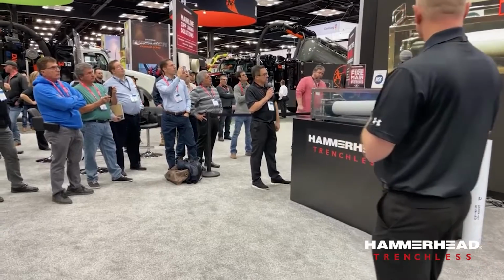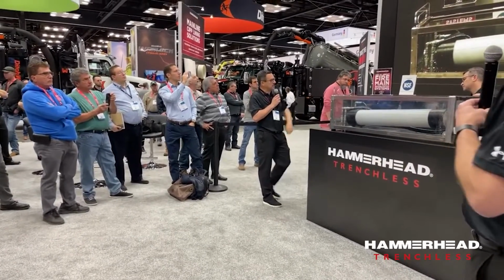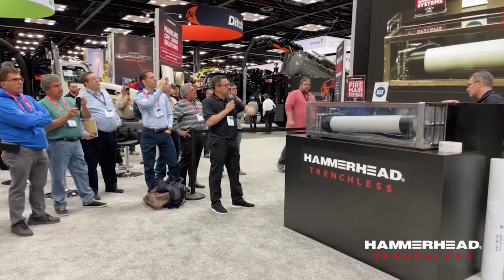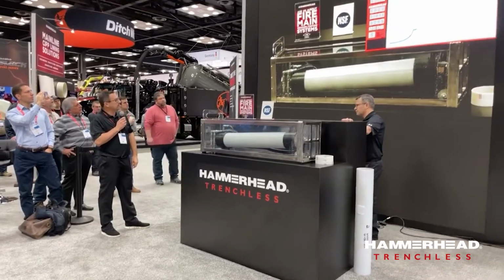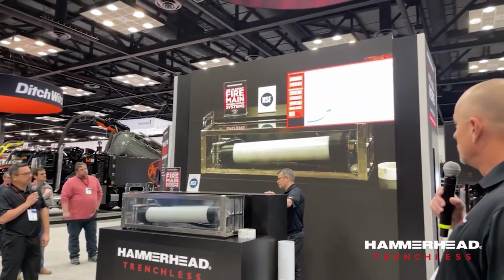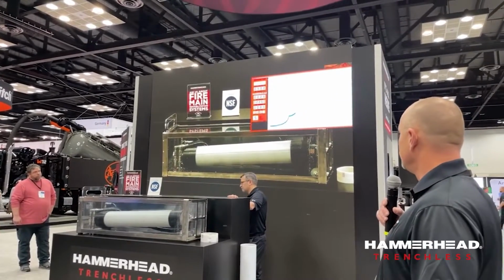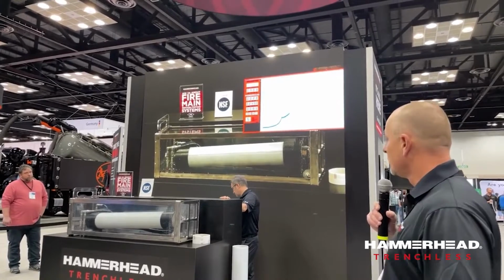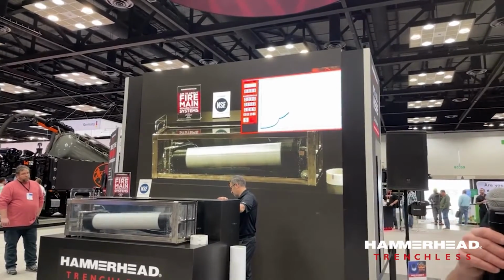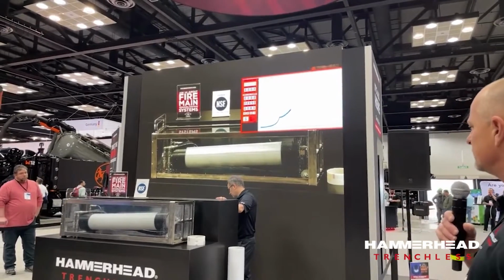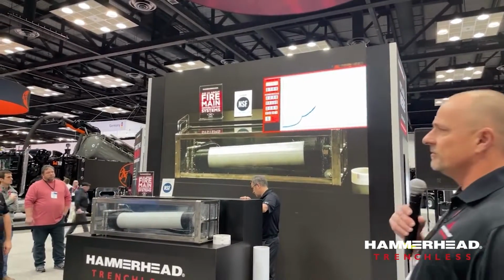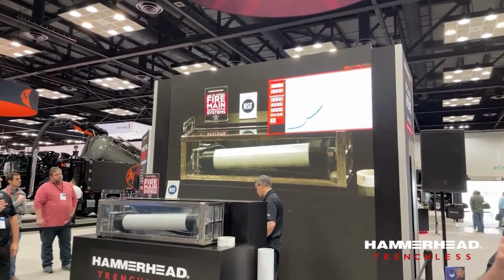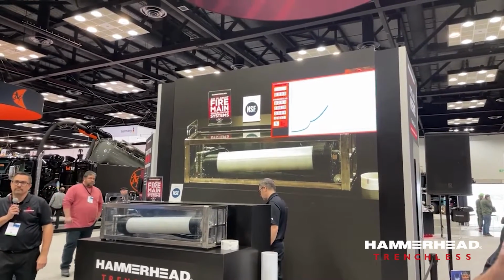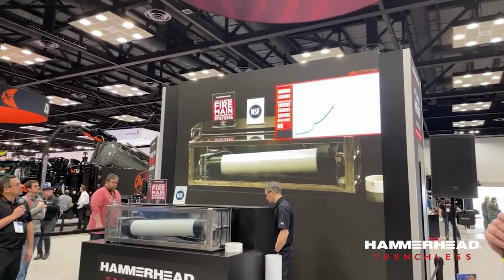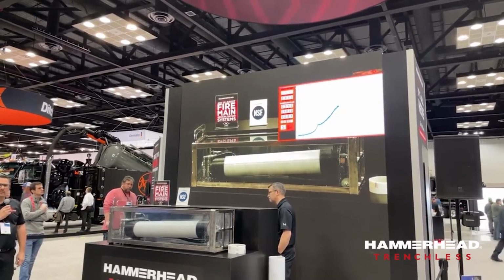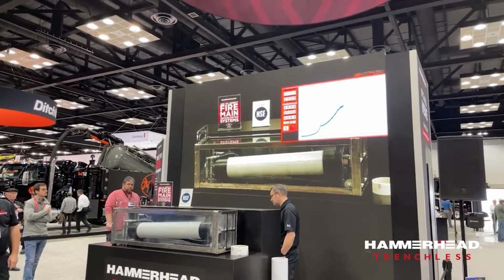That's it. So that's growing pressure inside this CIPP liner, and you see it's going up pretty good. You're at over, what is that, 150, 160 PSI? Doing a steady climb. What's that liner rated for? This is actually an R&D liner, so this one is about 500-600 PSI roughly in terms of burst pressure, which translates to about 125 to 150 PSI pressure. It's a 4-to-1 ratio. So we're going to start hearing cracking or something eventually. If you start cracking, you're going to see a physical burst. I hear cracking.